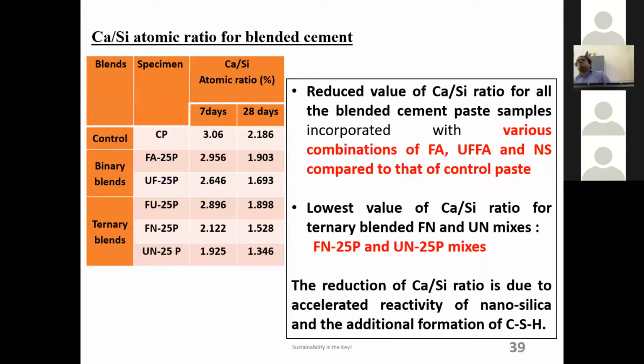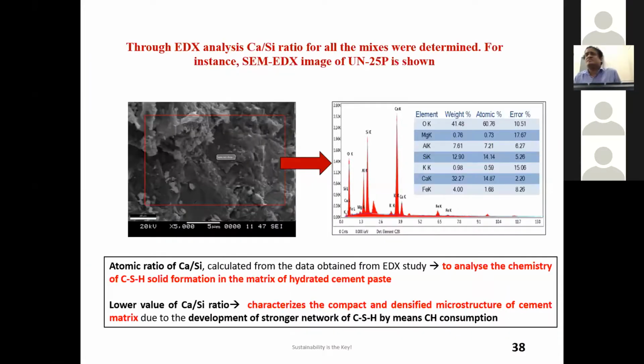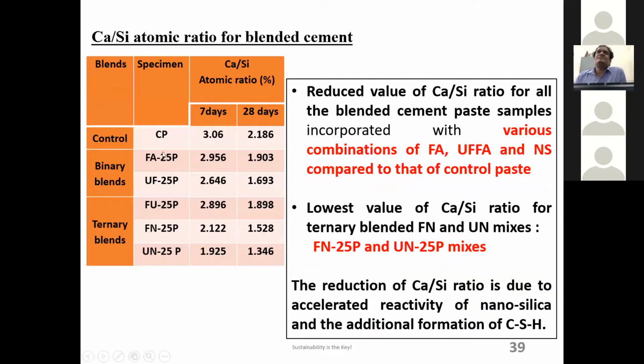Okay. So if you compare, for all the mixes, this kind of analysis was done. And with this Ca by Si ratio, you can see that from the control, going to the binary, from binary going to ternary, the Ca by Si ratio is reducing down, reducing down, reducing down. So that is good for me, actually. That is a benefit for me, actually. So more values I'm getting in case of the ternary blended mixes.